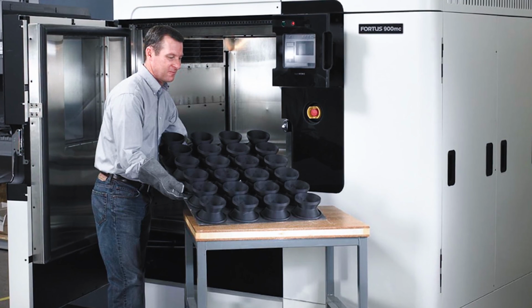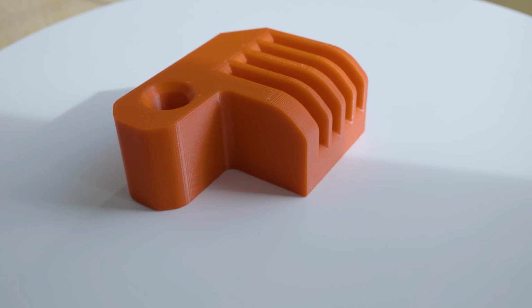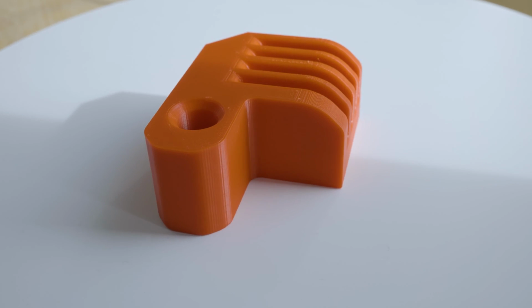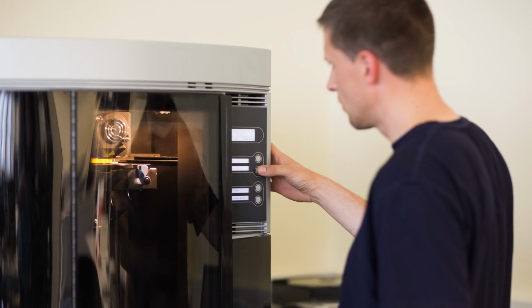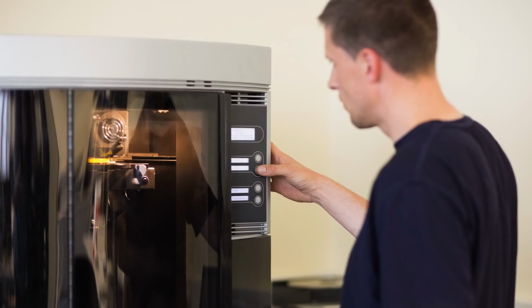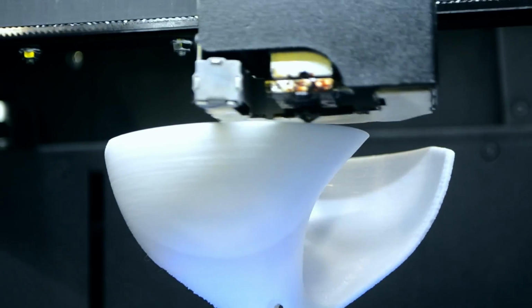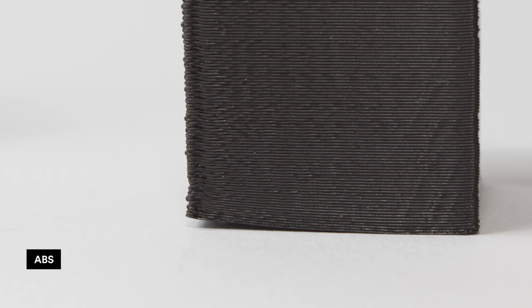Apart from nozzle and print bed temperature, another difference printing in ABS and PLA is that ABS typically needs an enclosure around the printer. As ABS is very sensitive to temperature changes during the printing process, an enclosure is required to trap the heat and to block the airflow. If the enclosure isn't there, a simple change in temperature or air drafts can make a part crack during the printing process. Besides that, ABS needs to cool more slowly than PLA. If not, it's possible the print can curl or warp.